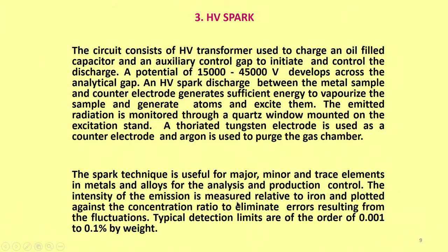That is how we use an internal standard, and it is a very important concept as far as chemical analysis is concerned using spectroscopy, because spectroscopy is always a relative technique. It is not an absolute analysis technique, never. So, the concentration ratio we have to plot rather than the actual signal.